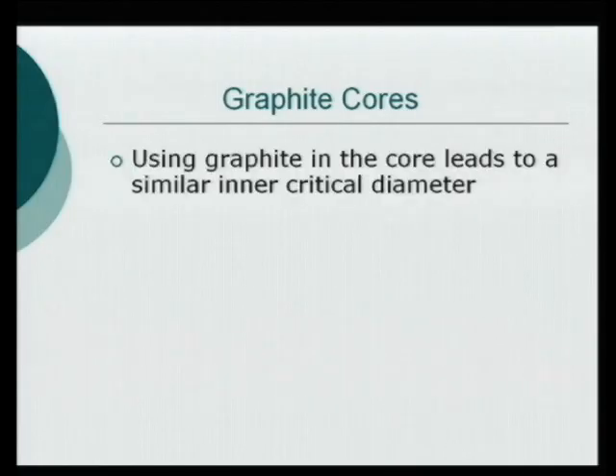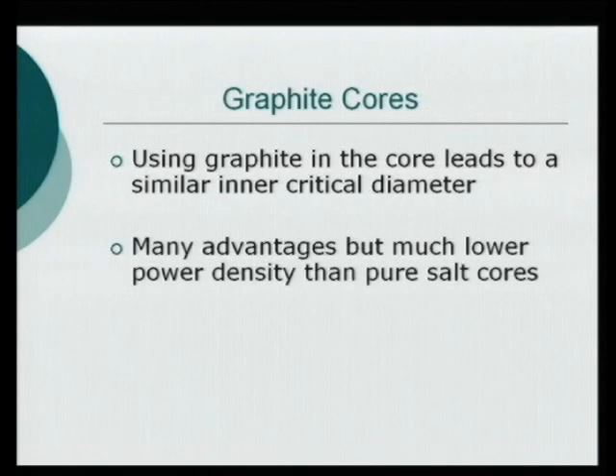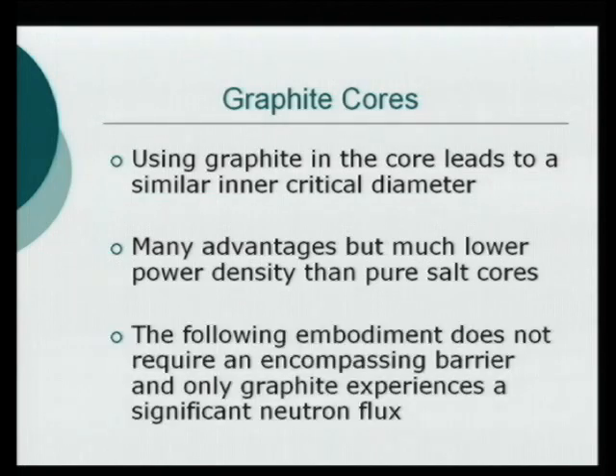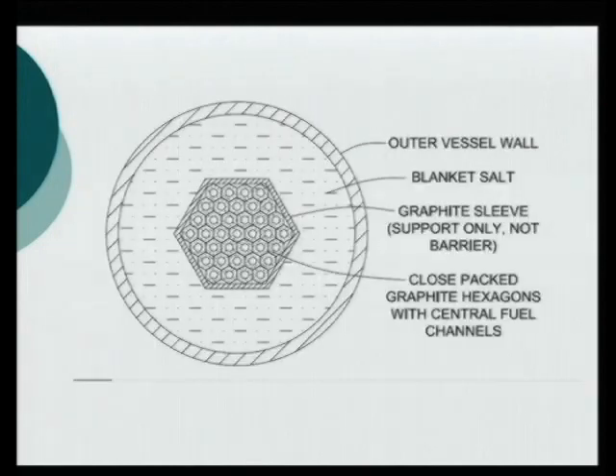Now graphite cores, adding graphite in there has some advantage. It's going to have a similar diameter actually, but it does lower the power density because it's not all salt. It's only about 10 to 15% salt then. But I just want to show an embodiment, an idea that has no real barrier material in a neutron flux, because what we know the metals can survive outside in contact with the salts, but it's the neutron flux.